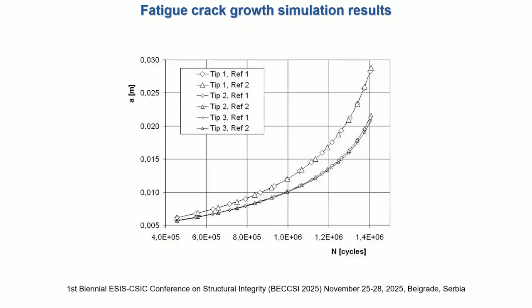And how do we know whether what we have simulated is good or not good? We have taken crack tip 1 as a reference. So we will repeat the simulation, taking crack tip 2 as a reference, and then we'll compare these two simulation results. What you see is that for simulation results with reference crack tip 1 we use diamond marks, and for reference crack tip 2 we use triangle marks. And so we have tip 1, tip 2, and tip 3. If you look carefully here, the simulation results overlap perfectly. So it's telling us that our simulation procedure is really fine.